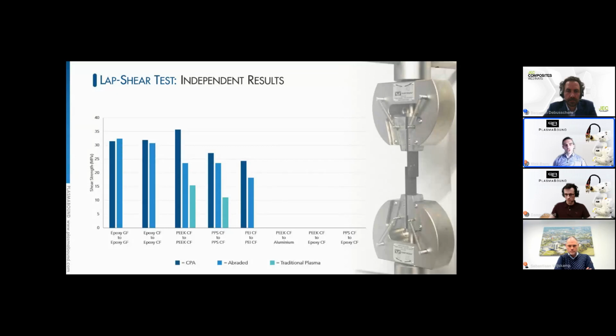And then when we moved into dissimilar material setups, where we have PEEK to aluminium, PEEK to epoxy CF, and PPS to epoxy CF, what we saw was quite interesting. With the PEEK carbon fiber to aluminium, no longer was the PEEK interface the issue, the common interface. We had treated it to a point where now the aluminium common interface was the issue, the adhesive to aluminium interface. And actually it failed at the aluminium side, which means that now the customer will have to treat the aluminium side in order to see how high a CPA prepared PEEK CF system is capable of going to, something they've never had to do before.